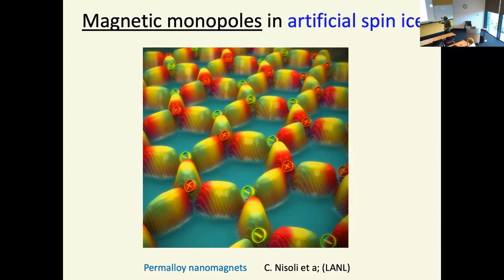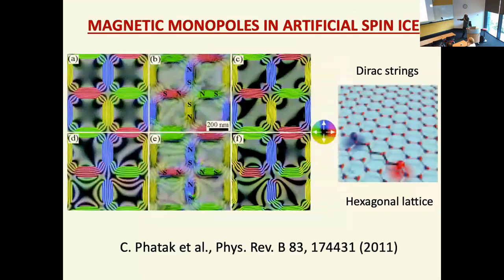And then you can create a configuration in which at certain vertices you have a point-like, spherically outward emerging magnetic field. So you have in artificial spin ice emergent monopoles, and therefore these are called magnetic charge. Electric charge, magnetic charge. When you have electric charge moving, you have electricity. When you have magnetic charge moving, you have magnetricity. There are papers about how to use magnetricity for something. And here's an experiment at the Argonne National Lab in which they looked at monopoles in artificial spin ice. This is what I was talking about. You create permalloy nano islands, and you have south pole, north pole, two in, two out, and you can create frustration, and then you create monopole and anti-monopole.